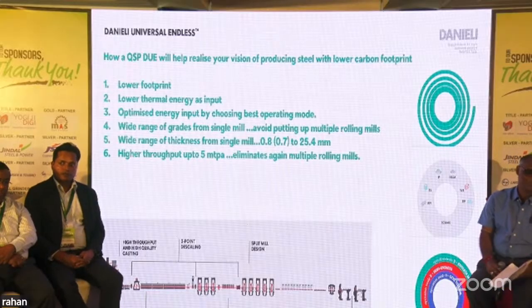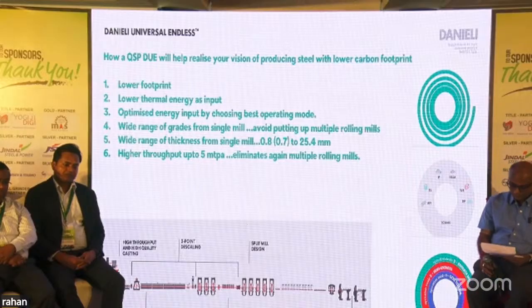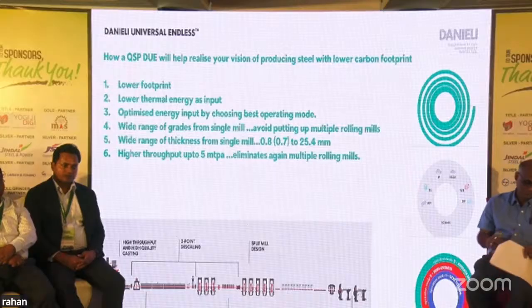And then the exit temperature has to be maintained at 1150 to 1180. So you're talking of only a delta of 200 degrees centigrade. On the contrary, if you talk of a conventional hot strip mill, the reheating furnaces will have a delta of, say, 45 degrees, that is ambient, to 1200 degrees centigrade. So here, in case of a tunnel furnace, which is the benefit of direct slab casting, there is less amount of thermal energy required.